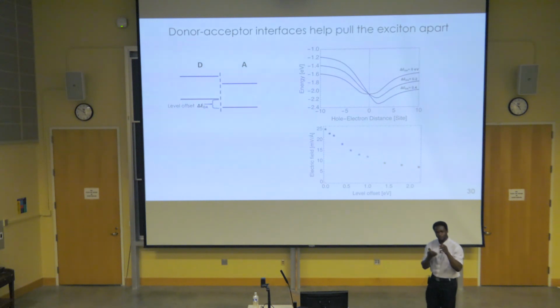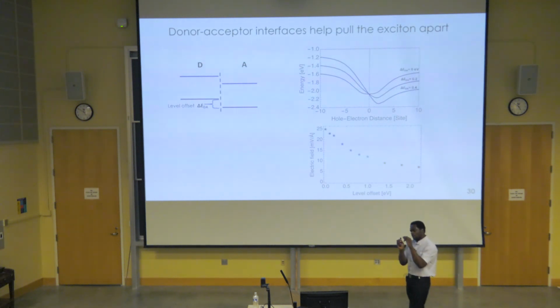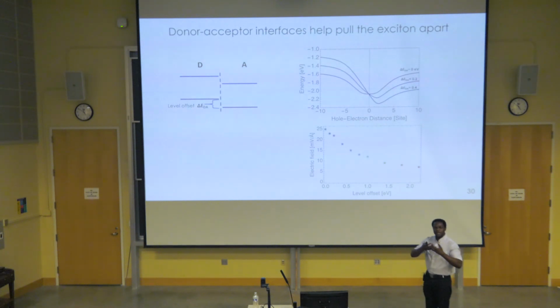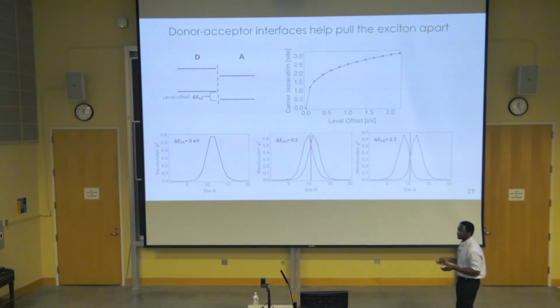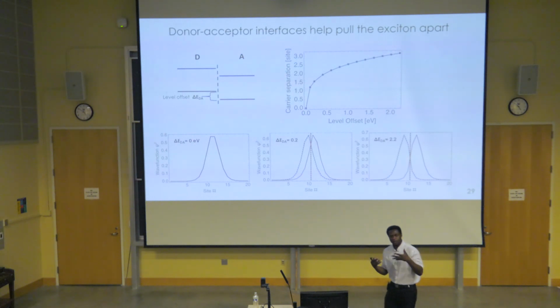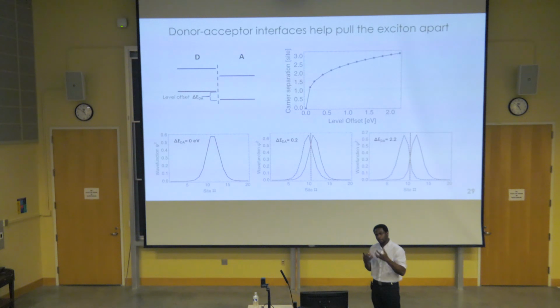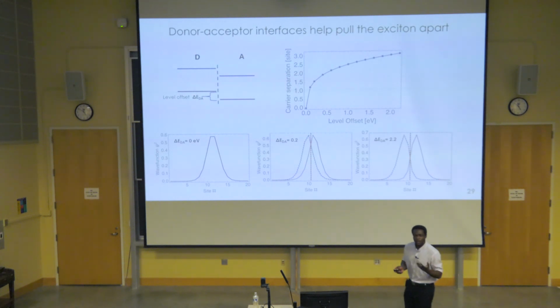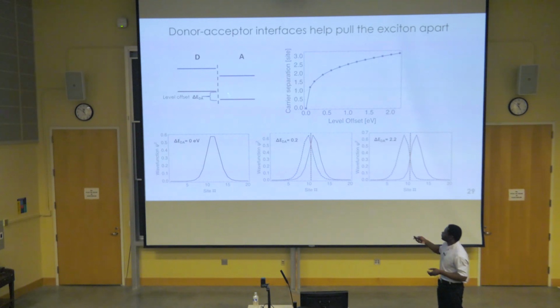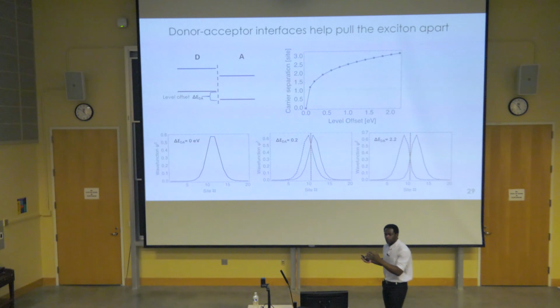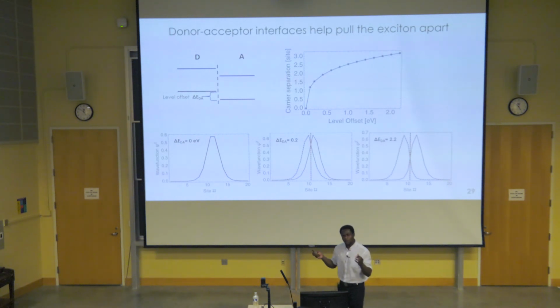Because of that level offset, we have a very large local field that by itself, without any externally applied field, is able to pull the charge carriers apart. It pulls the two charge carriers apart, as you see here. Because the charges are already pulled apart by that interface, you now require a smaller electric field to unbind the charge carriers. But obviously, in an actual device, you don't go to such a big level offset, because a large level offset will mean that you'll have a small open circuit voltage. So there's a trade-off.